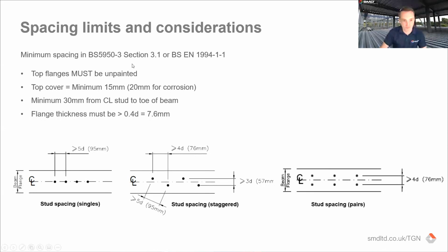So just a couple of other key limits: the minimum distance between the stud and the toe of a beam is 30 millimeters. That's the center line of stud to toe of beam. So that also limits the minimum flange sizes you need. Top cover recommended minimum is 15 millimeters, or 20 millimeters if you're protecting against corrosion. There are instances where you can go below that, but that is the recommended minimum. And usually your slab depth will provide that, because your fire rating for the slab governs the slab depth rather than the stud length itself.